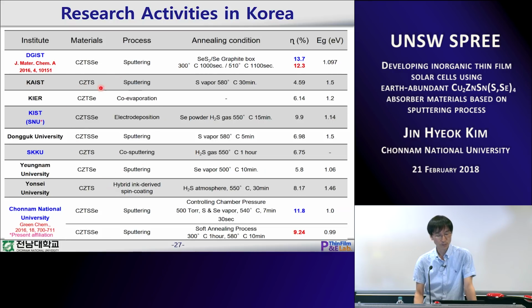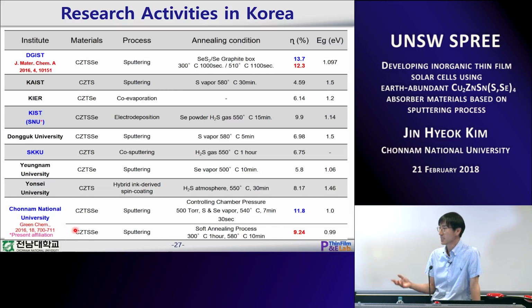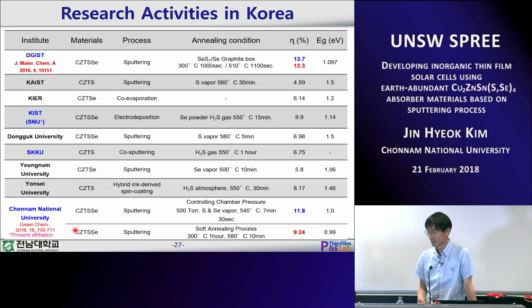And there are also other groups, and our university also reported 11.8% cell efficiency, maybe the second highest, and this is certified by KIER, Korea Institute of Energy Research. The result has not been published yet, but I wish we can publish it soon. Based on published results, we have 9.2% cell efficiency in Green Chemistry. This is a soft annealing process optimization. So maybe DGIST and Gina's group and our university might be the leading CZTS thin film solar cell research groups based on sputtering process. So we'll see.